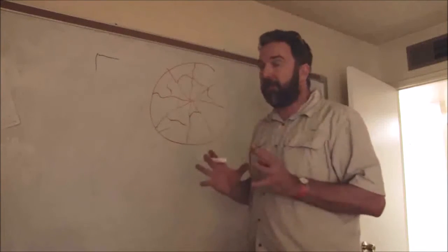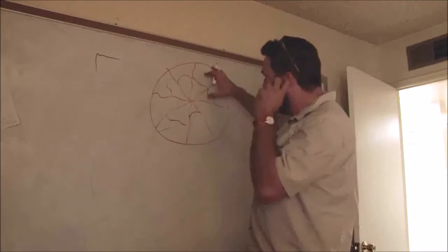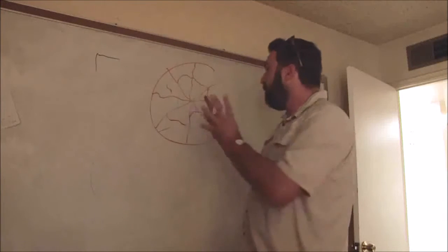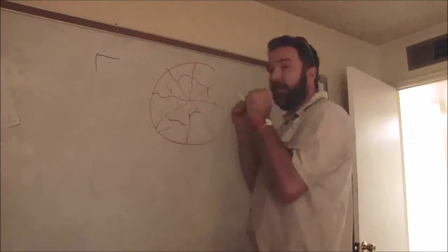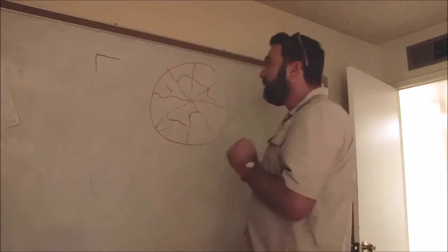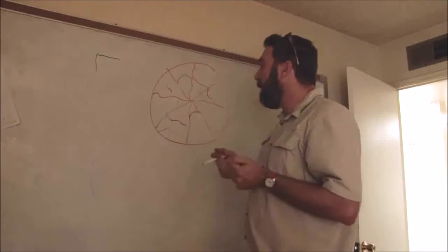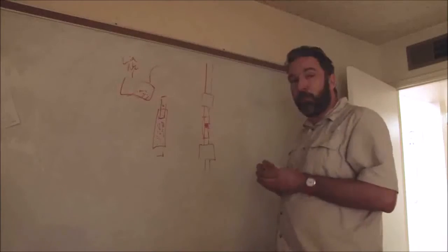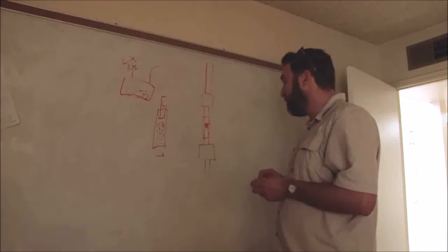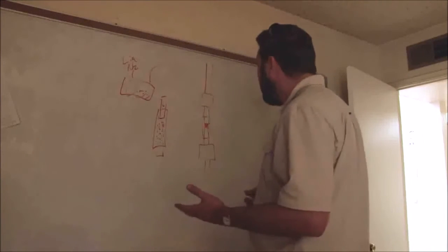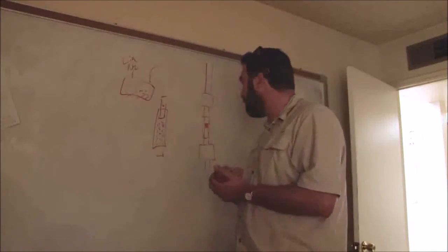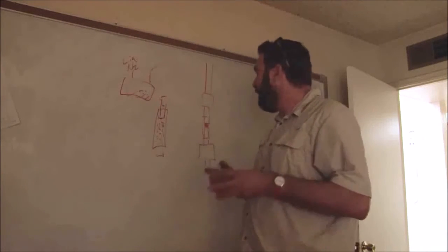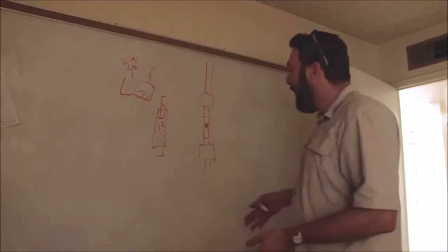So this is called the Hall-Petch effect. Basically, if we can get the crystals really super small, then because the surface area becomes so large in that same area, they stick together really, really solid. So you can take something like copper, an alloy that's 90% copper, and you can make it stronger than steel, if you can get the crystal size small enough. It's extraordinary. It's amazing how strong it is. One of the problems with nanocrystalline materials is that it's so hard. It has such good strength that when we go to test it, we keep breaking the testing rig. That's a wonderful problem to have.